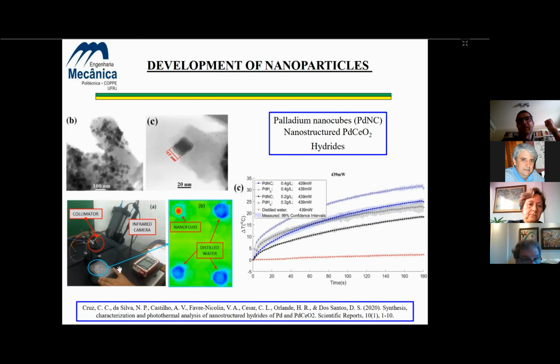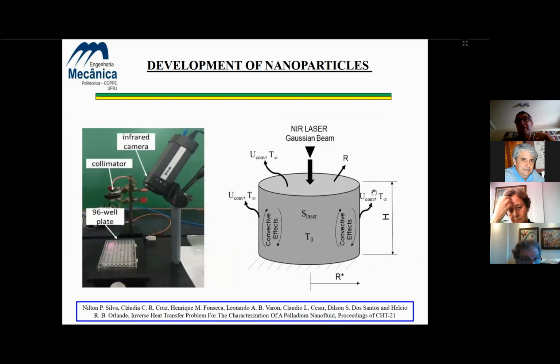Here's one of the wells in a 96-well plate containing the nanofluid, and the other containing distilled water as a reference, as a basis. And we can see very large temperature increases for different concentrations of nanoparticles. So actually, those nanoparticles increase the absorption of the laser energy, and then we investigated further these effects by solving the inverse problem